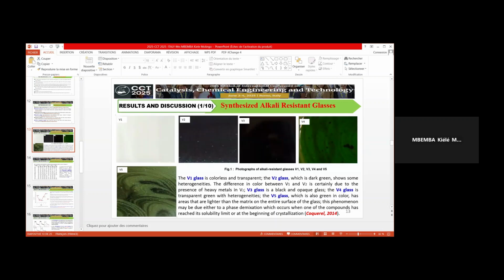V3 glass is black and opaque. V4 glass is transparent green with heterogeneities. The V5 glass, which is also green in color, has areas that are lighter than the matrix on the entire surface of the glass. This phenomenon may be due either to a phase demixation, which occurs when one of the compounds has reached its solubility limit, or to the beginning of a crystallization.